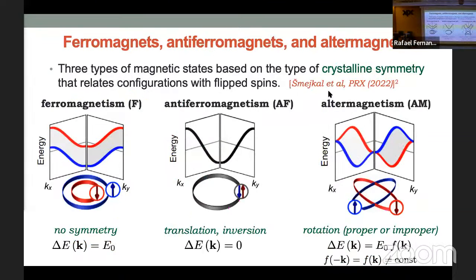Now, again, this gives me these three different classes. And again, these are two papers in PRX that I strongly recommend by Libor, Helena, and Tomas. So you can think of how the symmetries that leave the system invariant, combined with time reversal, determine the splitting of the spin up and spin down bands. Okay? If there's no symmetry, there's a uniform splitting, this is the ferromagnet. If the symmetries are either translation or inversion, like for example, if you have Néel order or staggered order in a honeycomb lattice, that is Q equals 0, but it's related by inversion, then this gives no splitting, and this is an antiferromagnet. And an altermagnet is when you have, combined with time reversal, a proper or an improper rotation, and then you get a modulated splitting, so on average it's 0, but it has nodes and it's even in momentum.